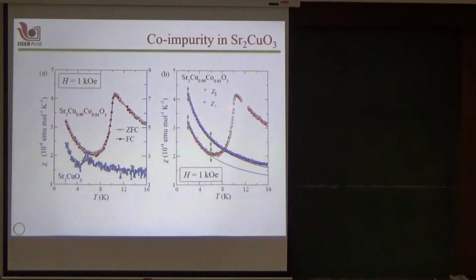And the system now behaves in a very anisotropic manner. So this is the susceptibility parallel to the chain, and this is susceptibility perpendicular to the chain, and the transition is seen only when the field is applied parallel to the chain. So this is the antiferromagnetic transition. I want to point out that this is different from the zinc impurity where the transition was suppressed. Here the transition temperature has increased.